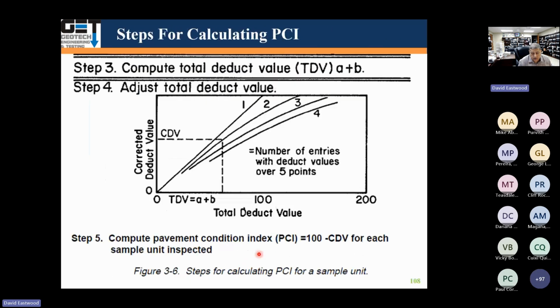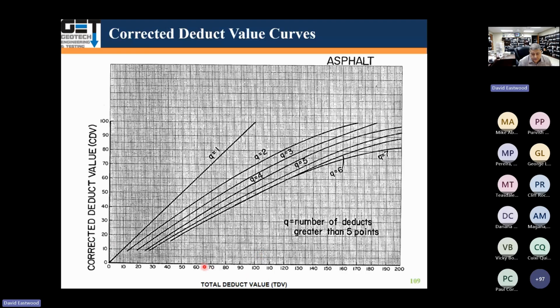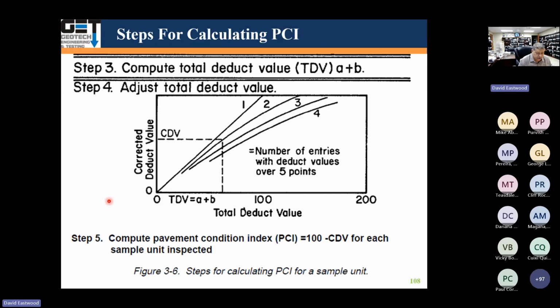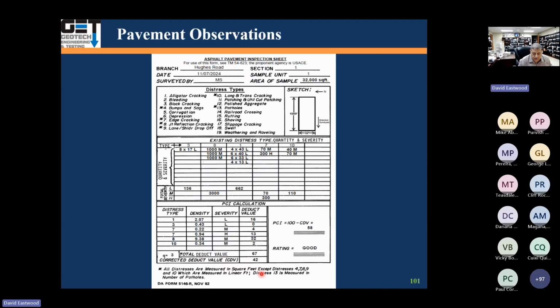So if you go there, 87 and 3, Q is 3. The Q is the number of deducts greater than 5 points. So you go over here, you get roughly 45. Corrected deduct value. Okay, so that's the correct 45. Actually, it's 42. So that's corrected value of 42. You subtract that from 100, you get a 58. That's your pavement condition index, which is considered good. So for this 1,000 feet by 32 feet, overall rating value indicates the pavement is in good condition.